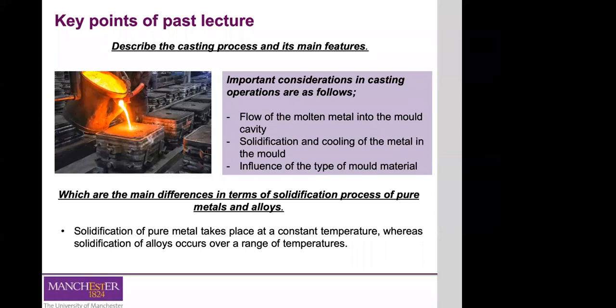An important difference to remember is the solidification behaviour between pure metals and alloys. Pure metals have a very well-defined solidification or freezing temperature, so solidification happens at a constant temperature. In the case of alloys, solidification happens over a range of temperatures — normally defined as the liquidus and solidus temperatures.